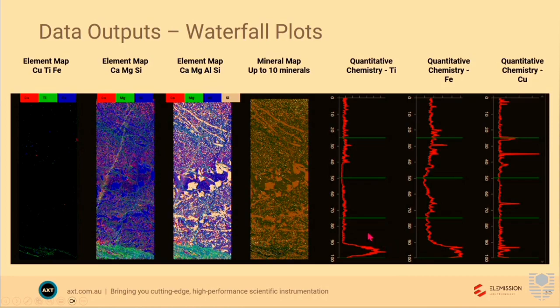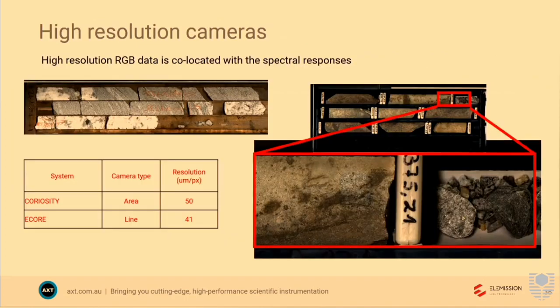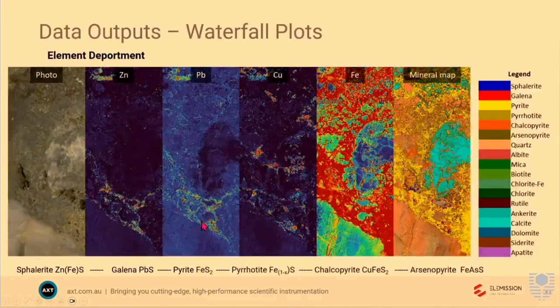So the theory is that you do a very low resolution scan of your sample, so it's really fast, and you can get maximum data on all your drill core, and then you go back and do a high resolution scan in those areas of interest. Additionally, it's got a high resolution camera, so we're just about to embark with a company that does image analysis. If you scan just a very narrow band down the middle of your core, it populates the rest of the core with mineralogy by the high resolution image analysis. So the image analysis is in the same order of magnitude as the same resolution.